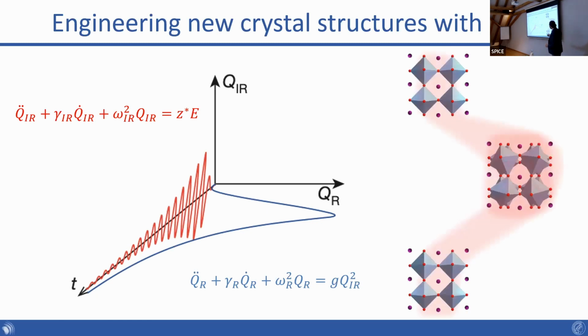And so what you can think of happening in this intermediate time regime, while this QR mode is ringing, is that you have a new crystal structure. And as I've mentioned before, this new crystal structure can then obviously have different magnetic interactions. And so this is what we can try to take advantage of to control the magnetic properties and achieve switching. The question that I'll address in this experiment that I'll show you is how we can use this effect to control the magnetic state in an antiferromagnet.